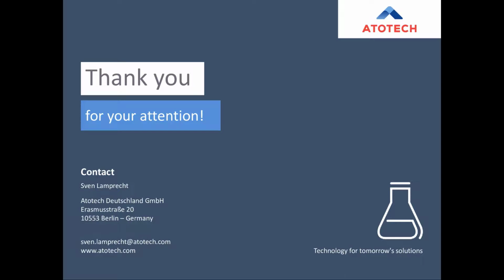Okay. All right. There is another question related to that. Is there a need for a special adhesion promoter for plating on molding resins? Yeah, well, molding resins are built up a bit differently than normal PCBs or FR4 or the epoxies used in PCBs. This has to do with some waxy components inside. So the adhesion promoter first has to start to de-wax those molding resins. And because the composition is also slightly different, you will also need a special adhesion promoter, just focusing on the molding resins. Typically PTH or electroless processes from PCB manufacturing will not work.